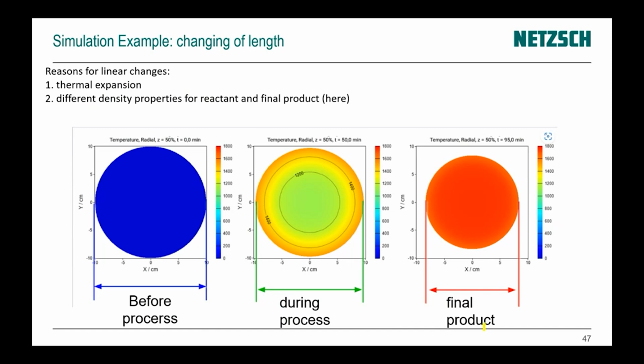So in this case, you can make a simulation of the length of your polymer during the curing process. And if you have different curing, different materials, then you can see the change of the length for one material and for another material, and at which temperature everything happens.